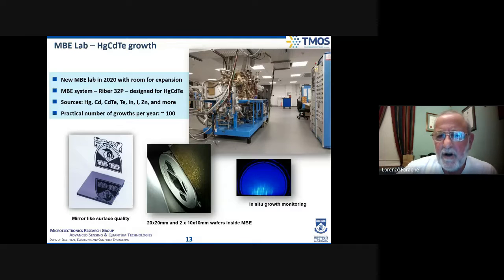MBE growth is a whole technology in itself, and requires an MBE system that's designed specifically for mercury cadmium telluride. It's a Riber 32P, a 3-inch system, where we grow mirror-like surface layers of mercury cadmium telluride on cadmium zinc telluride, which is the substrate that's lattice matched to the mercury cadmium telluride.